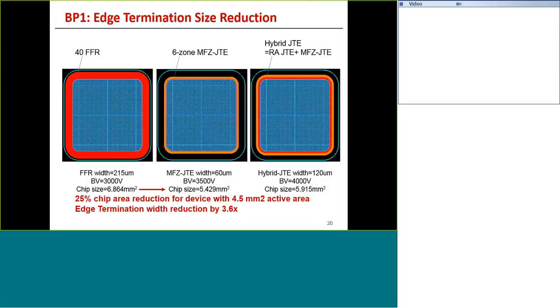So this chart compares the terminations from the point of view of space on the edge of the chip. I don't want to spend a lot of time going through the details here. Just want to mention that with the MFZ and hybrid JTE, the breakdown voltages are much better than for the FFR, and we can hit up to 4,000 volts with the hybrid JTE. The chip area is reduced by up to 25% for this small size device, about a 5 to 10 amp device in terms of the active area. The edge termination width itself is reduced as much as 3.6x by using these improved terminations compared to the FFR.